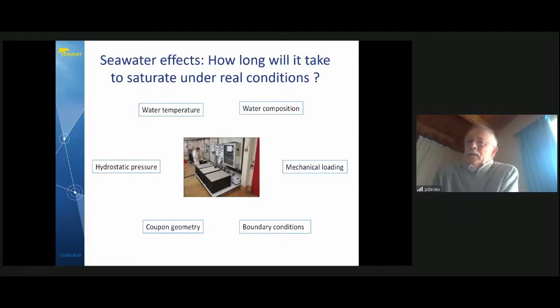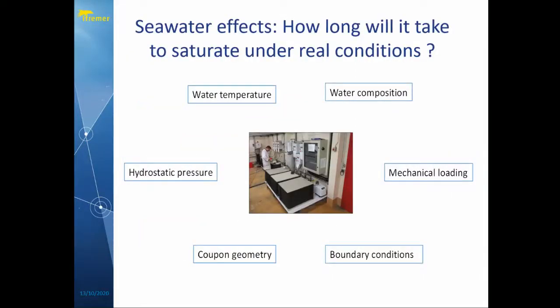So if we come back to seawater effects, one of the questions is how long it'll take to saturate under real conditions. And there are a number of parameters to use, in fact, to see what your water profile will be. So you can play with water temperature in the laboratory, accelerate your tests by heating up your water. You can play with water composition a little bit. That's going from seawater to deionized or tap water. You can play with coupon geometry. You can play with boundary conditions to get water in more quickly. And then there's mechanical effects, which I'll come back to in a minute.